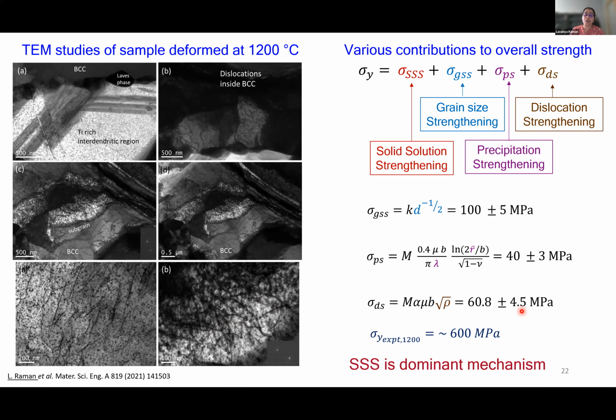From the XRD we can estimate, but when we have multiple phases, it may be very difficult to identify what the contribution is from BCC, which is the major phase. The XRD is always a bulk technique, right? Yeah, that's true. That's why I had to go for TEM, to get how the BCC phase is affecting or contributing to the overall strength.